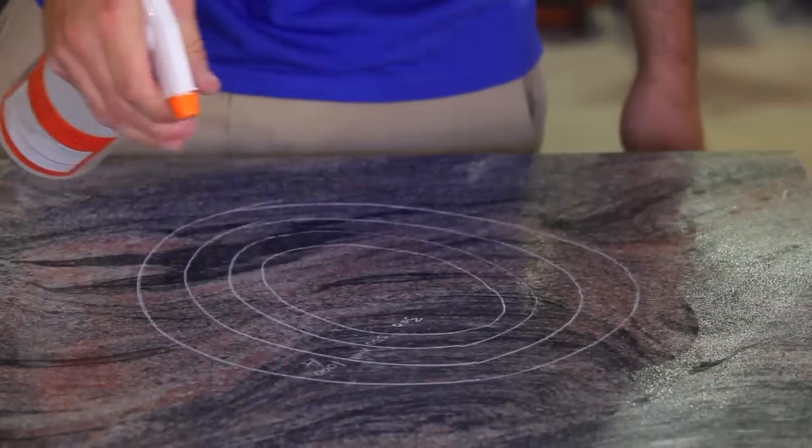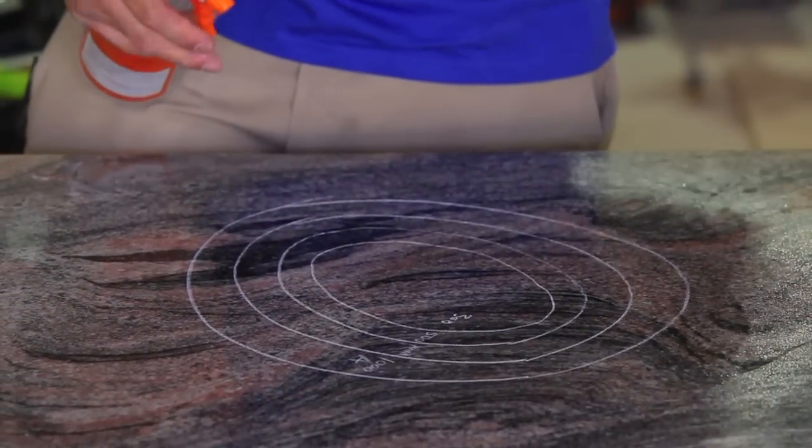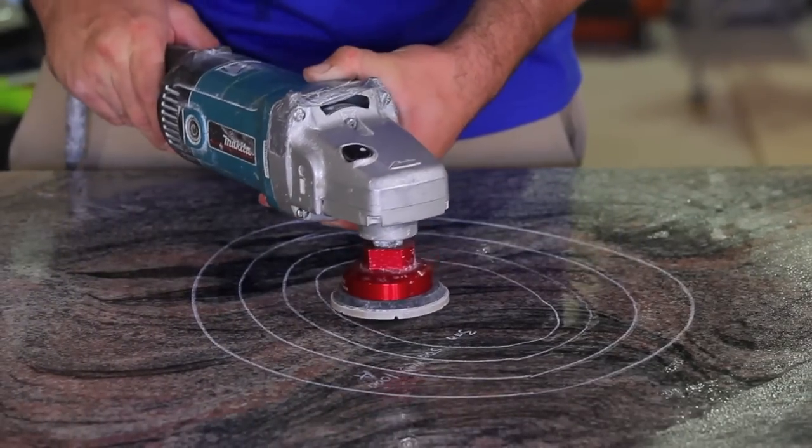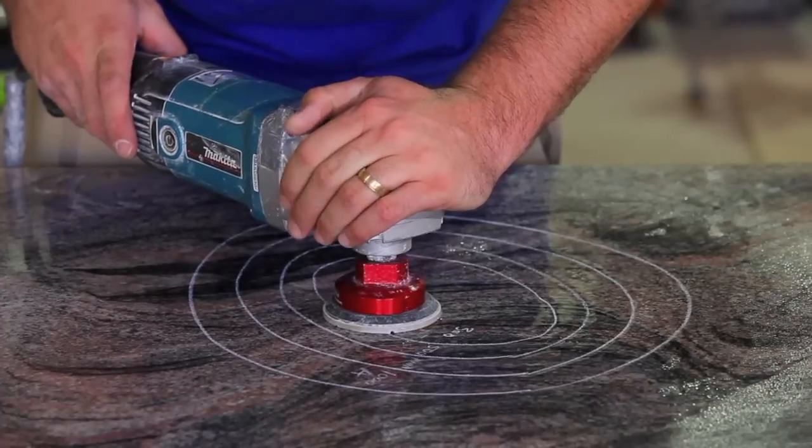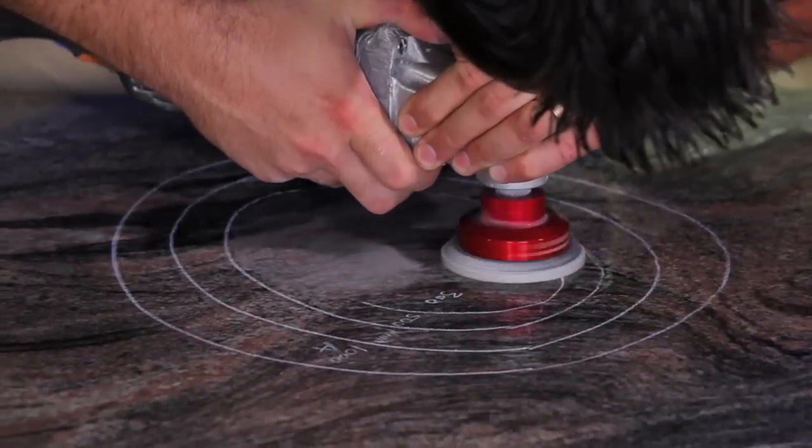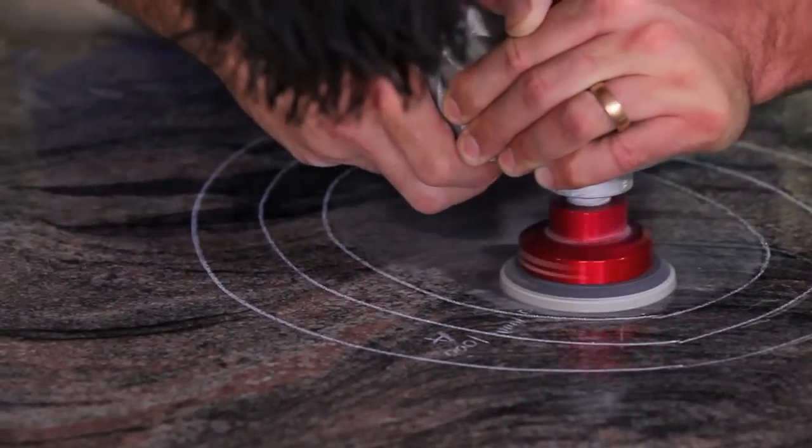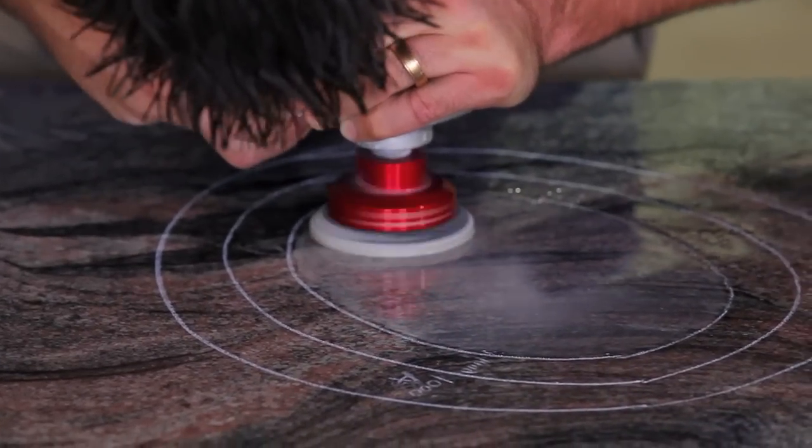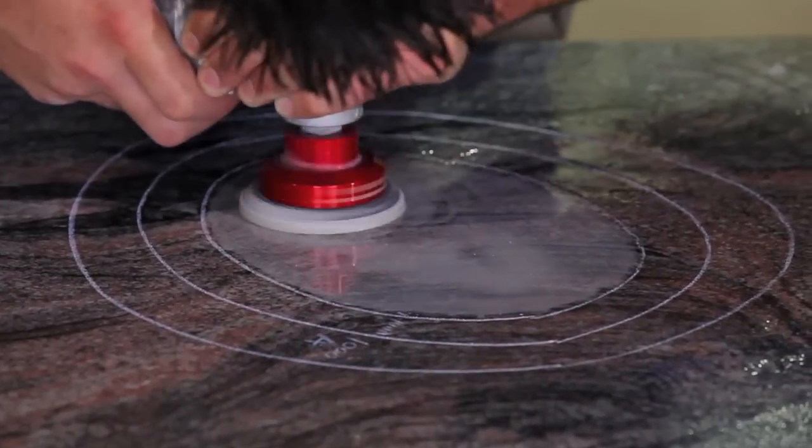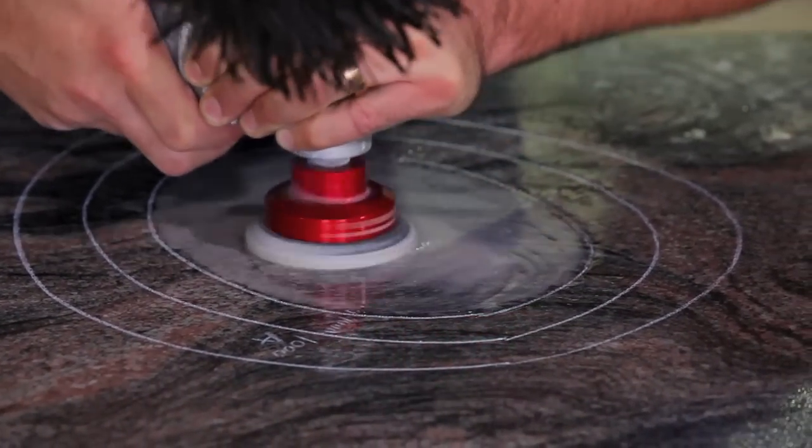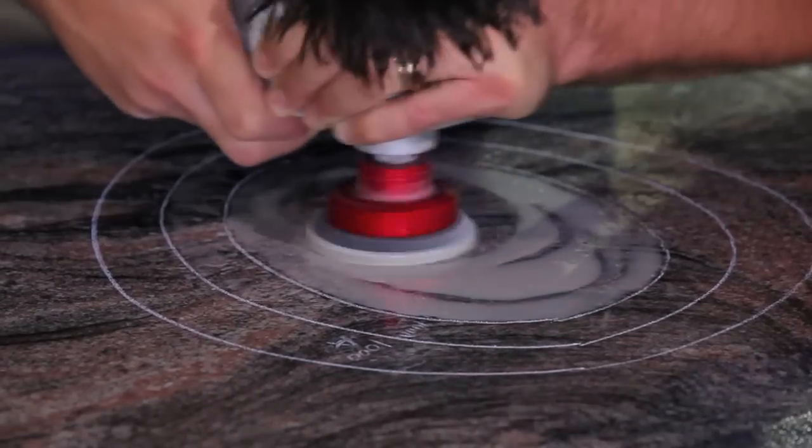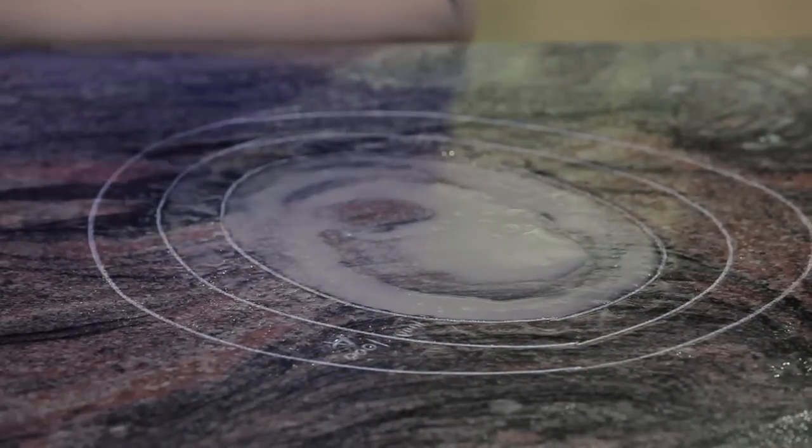Spray down your area with water and continue with your next step. I prefer to start with the outer ring of the scratch pattern first and work my way towards the center. This is because often subconsciously you will forget to work enough on the outside resulting in poor overlapping and a scratch pattern that is dull around the outer ring. The ability to precisely control the machine is very important with this procedure. You must be able to go up to the line but not over it so that you do not interfere with your next step. Notice how on this step the slurry is generating very quickly. The stone is cutting very fast and even though it is a 500 grit it still removes a significant amount of material. You must pay attention and not go too far. When you feel you have completed your step, remove the machine and clean up the area and dry it for inspection.